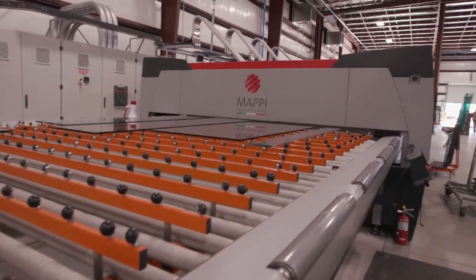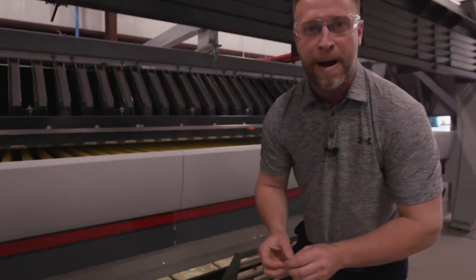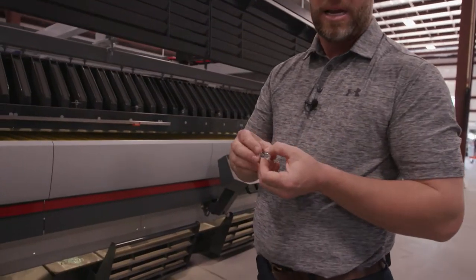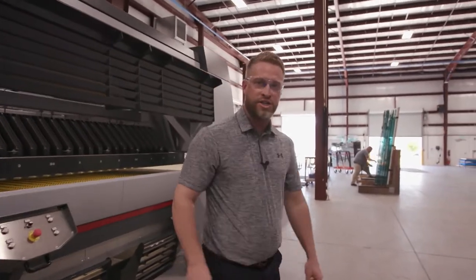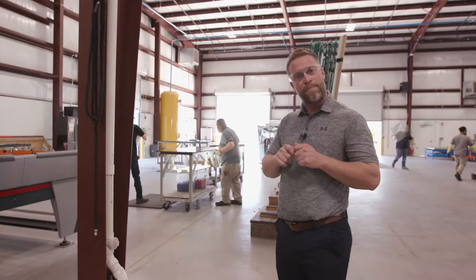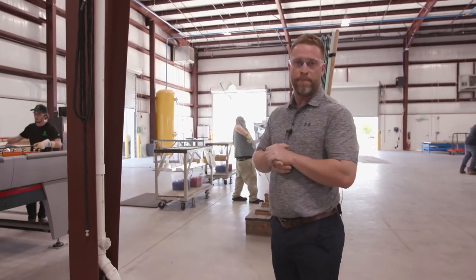Multiple shower door panels are about to go into the heat chamber. They get heated to about 660 degrees Celsius, which is about 1,200 degrees Fahrenheit. Not all glass makes it through the furnace properly — if it has a nickel sulfide or some inclusions, you'll see the small pieces and the tension haze in the center. Once the glass is done quenching, it comes out to the unload section. We do one last check in our QC department, where technicians look at the glass, check the paperwork, measure it, and make sure there are no seeds or bubbles from the float company.